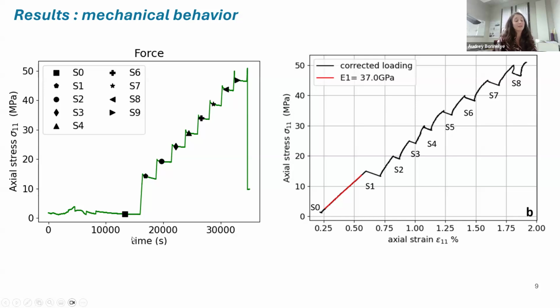Those experiments are extremely time consuming, first of all because of the time that is required to take the pictures, and also the time that is required to reach the appropriate conditions in terms of temperature, so we have the good hygrometry inside of the chamber of the SEM. So he's been loading his sample, and you can see the stress strain curve on the right that is corrected from the deformation of the vessel. And so S1 to S8 are the steps and the image steps that he did.